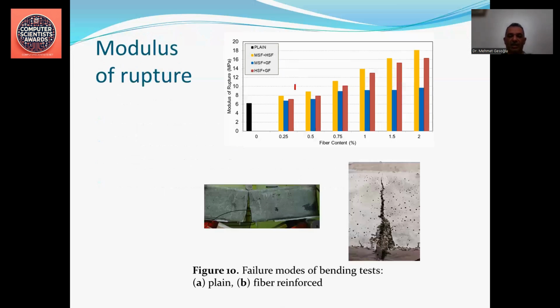This shows the variation of the modulus of rupture, and this figure shows flexural failure of plain concrete, while this shows the flexural failure of fiber reinforced concrete. As you see, fiber reinforcement provides bridging and anchorage that prevents the fracture of concrete. Plain concrete has the lowest flexural strength, while the micro steel and hook steel fiber have reached the highest strength at 2% fiber content.